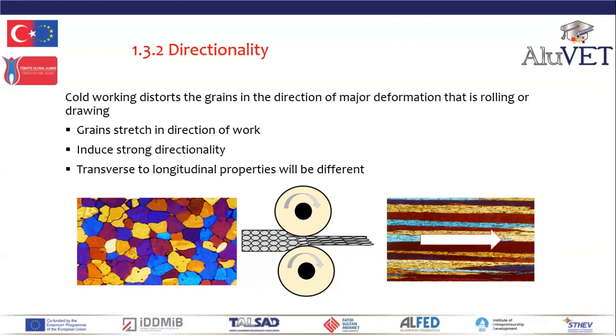Now, when we roll a slab, we control and stop transverse movement. So when we roll a slab, we reduce the thickness. We roll the slab so it grows in length, but we constrain the sides so it doesn't move transversely. So we restrict the spread sideways, so growth is longitudinal. So the strength increase will be marginally greater longitudinally than transversely. That is because the sideways deformation is minimal, so the resultant cold rolled properties transversely and longitudinally will be slightly different. This means that cold worked metals exhibit directional properties in the direction of maximum cold work.